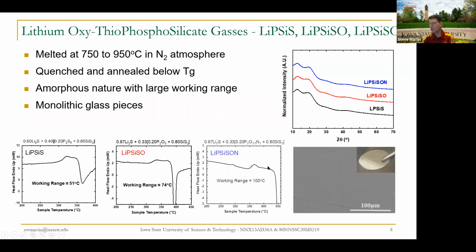And as we add nitrogen, we push it out even further, about 100 degrees. And that gives us a range of temperature where the liquid, the glass, is viscoelastic. We can stretch it, we can pull it into thin films. We can form it into thin films, just like the polymer people do in extruding their thin films. And the thin film is important because we want to have fast ion conduction across the battery with very little resistance. I'll show that in a moment. And this just shows a picture of the surface of a glass, and here's a typical sample.